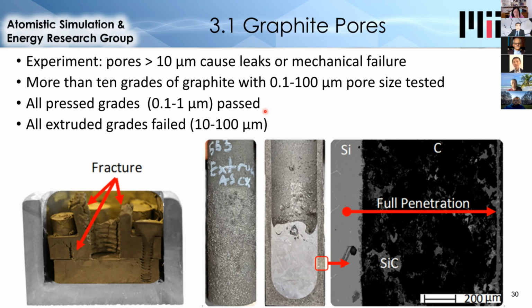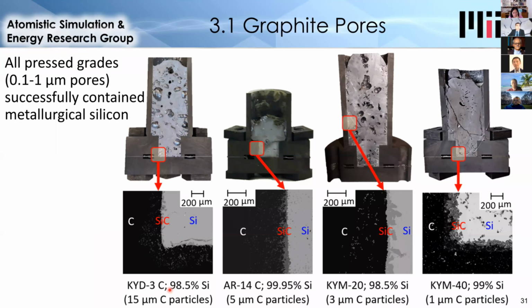Unfortunately, they don't make graphite with pores between 1 and 10 microns because of the discontinuity between manufacturing methods. So the next set of graphite materials had pore sizes between 0.1 and 1 micron. So essentially, we would predict all of these to pass, or at least most of them with pores smaller than 1 micron. And in fact, in these experiments with 4 different grades of graphite, with pores between 0.1 and 1 micron, they all successfully contain silicon, forming a thin silicon carbide layer shown in these SEM images on the bottom. This medium gray color is silicon carbide.